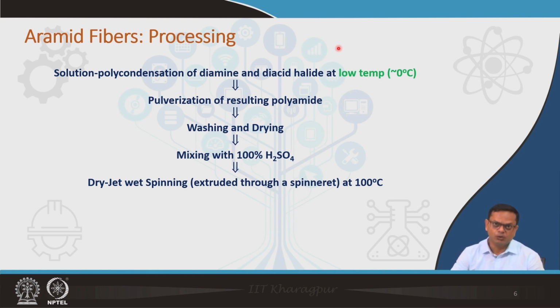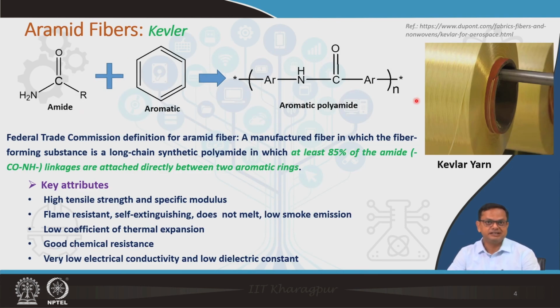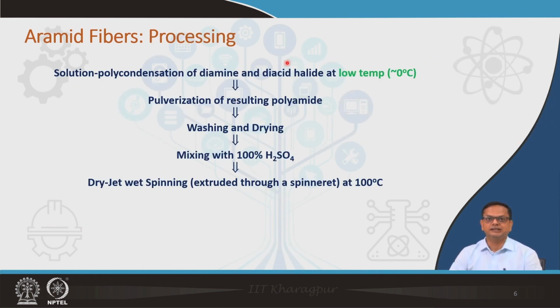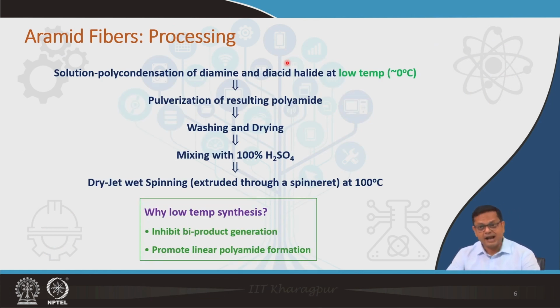Now, the question here is why do we need to go for this low temperature? This low temperature is extremely important to inhibit byproduct formation. What do we mean by byproduct formation? Again, as I mentioned earlier, I want this amide group to be attached between two aromatic rings, and that should be around 85%. If there is something else happening, that we are calling byproduct. So, yes, it has to be done at low temperature basically to inhibit byproduct formation,